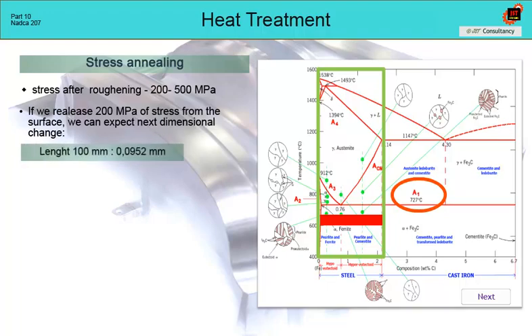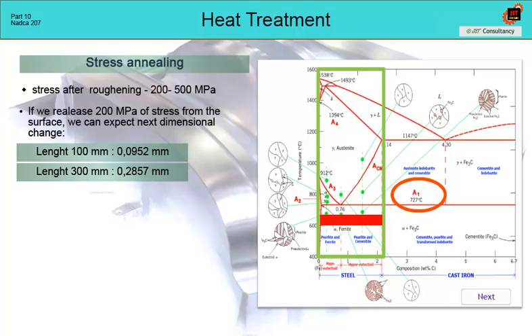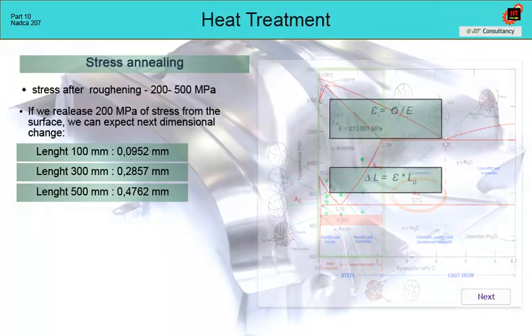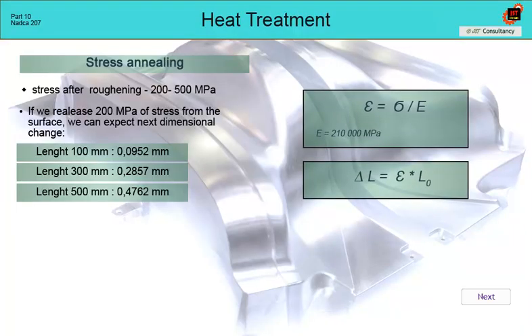For a characteristic dimension of 100 millimeters, 0.0952 millimeters, for 300 millimeters, 0.2857 millimeters, and for 500 millimeters, 0.4762 millimeters. The calculation is according to this formula. For large inserts, we can have a dimensional change of the order of about half a millimeter. That is not a small change.